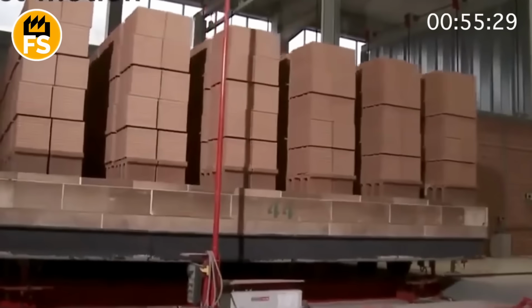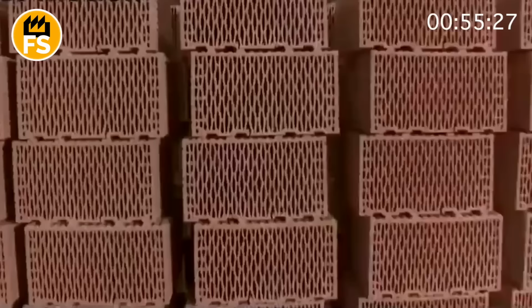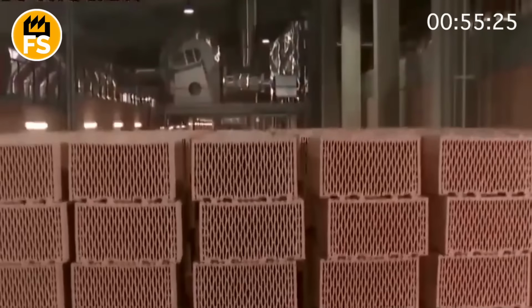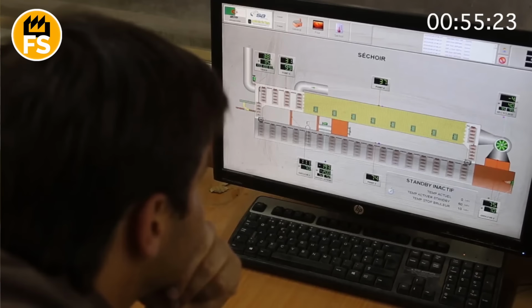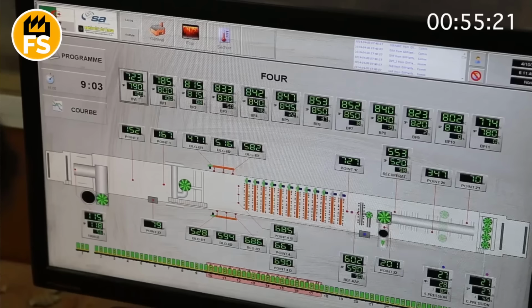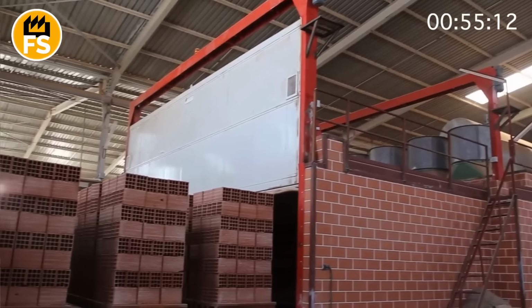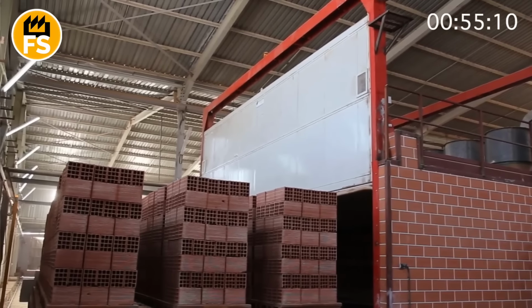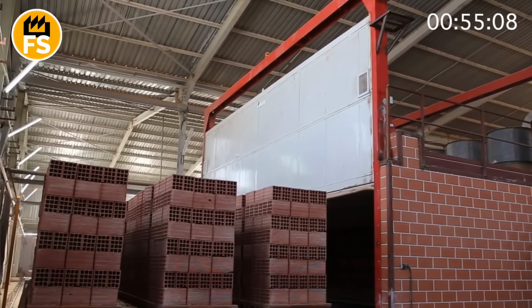But exiting the kiln is just as important as entering. The last third of the way, the brick passes through a controlled cooling zone. Its temperature is just as gradually lowered. Too rapid cooling will lead to thermal shock, and the brick will simply crack. When the kiln car finally emerges from the other end of the tunnel, it carries finished bricks. They are hard as stone.